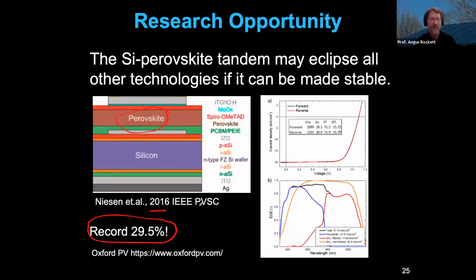So in our silicon perovskite tandem, we have a high efficiency perovskite material, which is collecting the blue photons and letting the red and the yellow photons through. And those are being captured by the silicon. And you can actually see this in this chart down at the bottom here. This is a so-called external quantum efficiency chart. The blue curve here is from the perovskite solar cell, and the red curve is from the silicon.